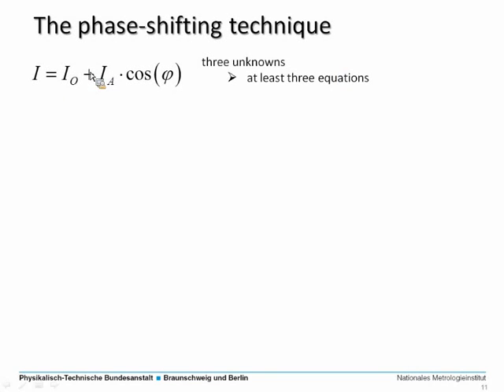Well, back to theory. This is the formula which describes a two-beam interference. You have the intensity, which you can read out by a camera, and this is calculated from the bias intensity of the two overlapping beams and the modulation of the interference pattern, in this case, if you use a coherent light source such as a laser. But what I want to point out in this formula is that, if you know this quantity from the measurement, at least the value of the camera pixel, you have three unknowns, and what you want to have is this interference phase in order to perform the length evaluation.